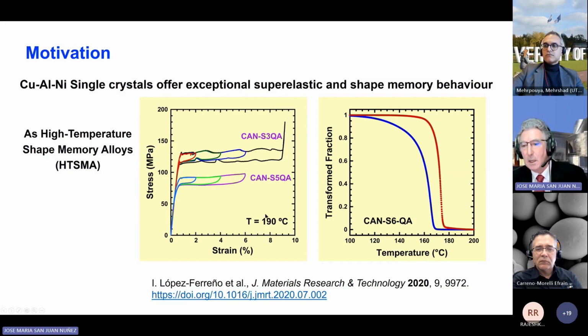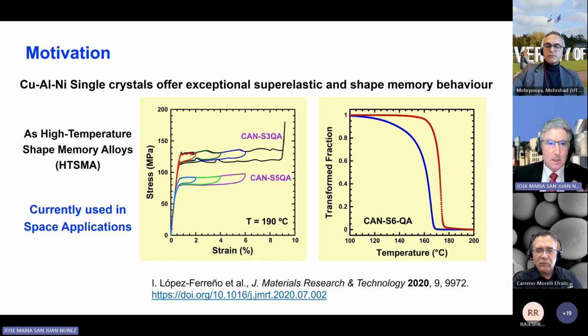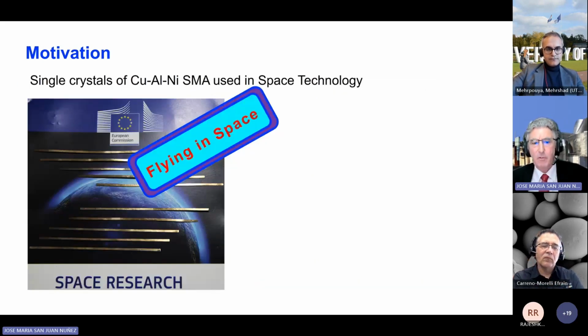And these single crystals can be managed in order to have all the transformation temperatures above, for instance, 160 degrees centigrade. So this means that they are working at high temperature, and we can control the transformation temperature between 100 and 200 degrees centigrade, basically. At present, these single crystals are currently used in space applications. And in fact, they are already flying in space.